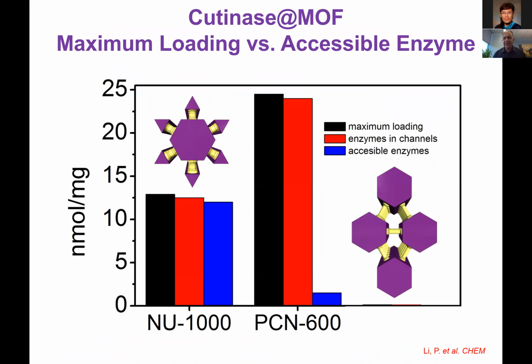To cut to the chase, these are the two best materials. If you have hexagons only with channels, and if you have the triangle and the hexagons with channels. So in black, that's when we put the enzyme at the beginning. In red, that's after we clean up the surface. So you could see when we have hexagons only, we could put twice as much enzyme. That's not surprising because we cannot put any enzymes in the triangles, so that's fine. More importantly is accessibility. Look at the one with the triangles and hexagons.